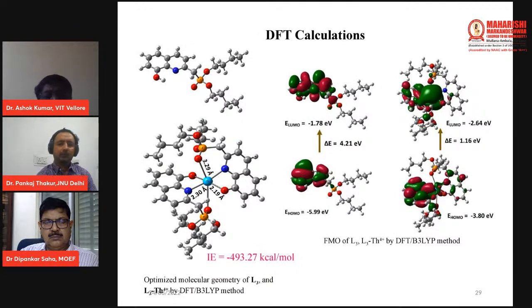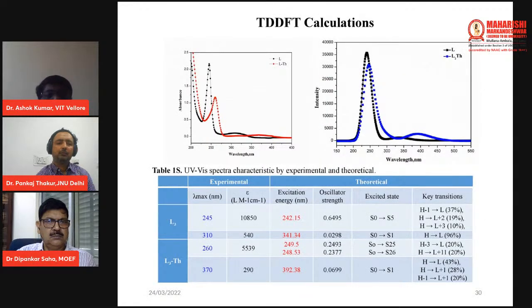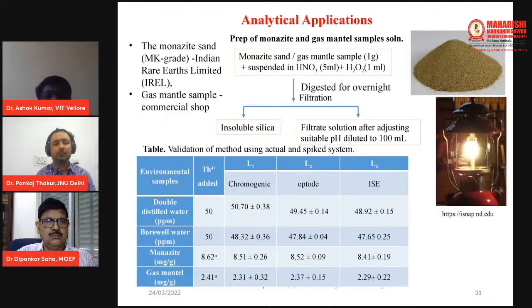The theoretical studies show the HOMO-LUMO formation in the case of the ligand on the same site, while in the case of the complex, the HOMO is forming on the quinoline side and the LUMO is forming on the thorium side. That shows there is an LMCT concept, ligand to metal charge transfer. So all these are further evidenced through calculations. What the experimental evidence shows is well supported by the theoretical studies.